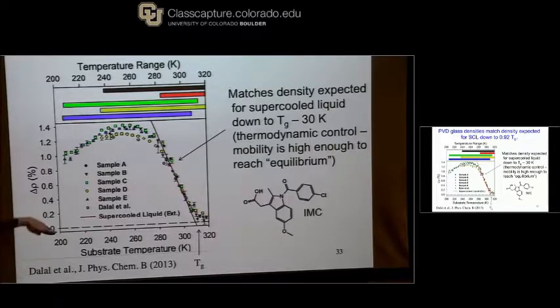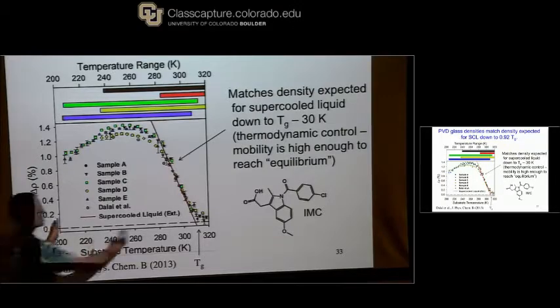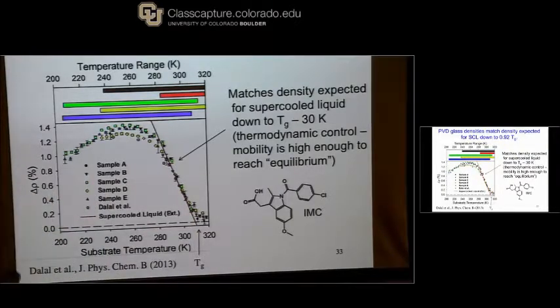This scale tells you how much more dense the vapor deposited glass is than the reference glass, which was the liquid cooled at 1 Kelvin per minute. So all of these substrate temperatures are giving us glasses that are more dense than the liquid cooled glass. And then there's one other important thing here.